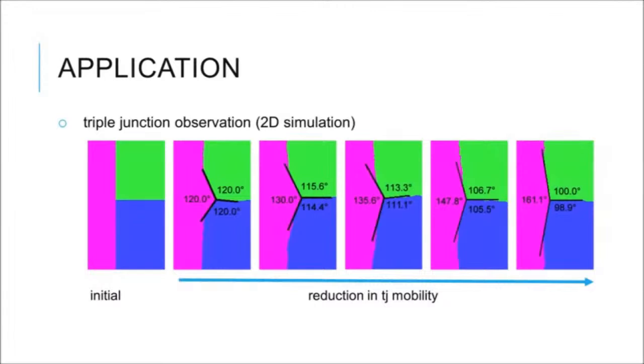However, if we reduce our triple junction mobility, the angles change dramatically. For a really low mobility of the triple junctions, we get two dihedral angles of only about 100 degrees, and one of about 160 degrees. So apparently there are inherent changes in the junctions.